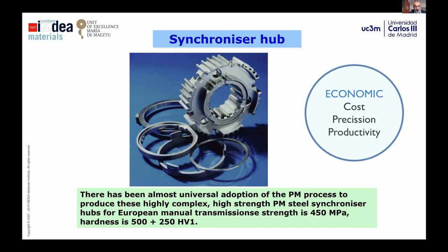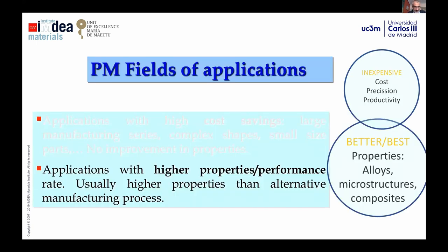If we go to the second field of application, it's the completely opposite field of application. In this case, through powder metallurgy, we can produce parts with much better properties than any other alternative manufacturing process. Why? Because powder metallurgy can assure, by different ways, a better microstructural control, a better chemical control of the composition, no segregations, and a lot of different things that can improve a lot the properties. In that case, powder metallurgy is the best way to obtain one determined part. One example of this field of application is high-speed steels.